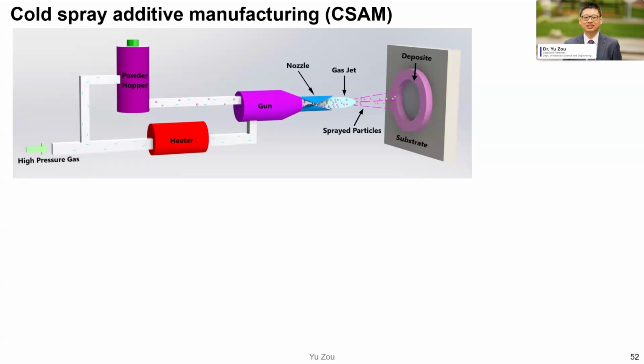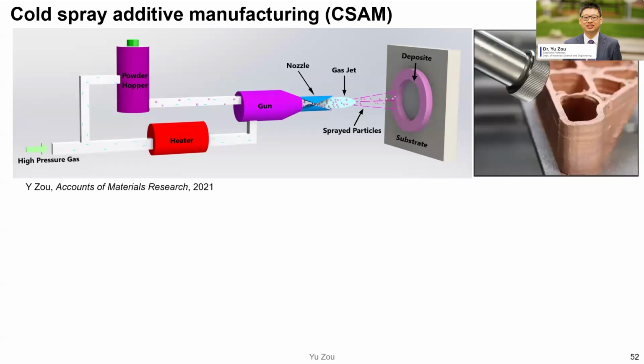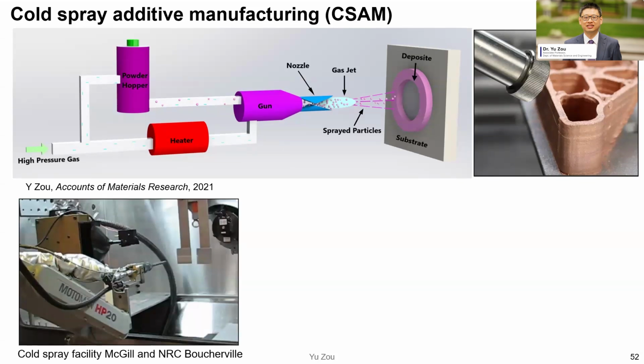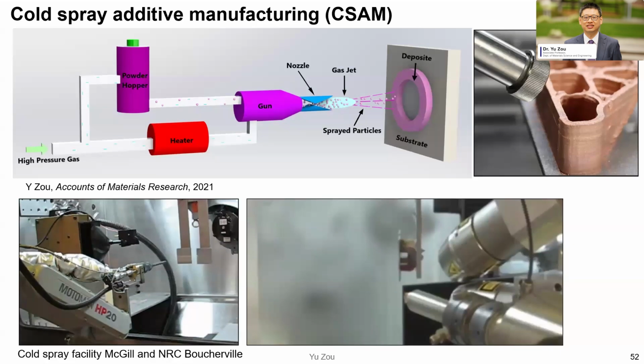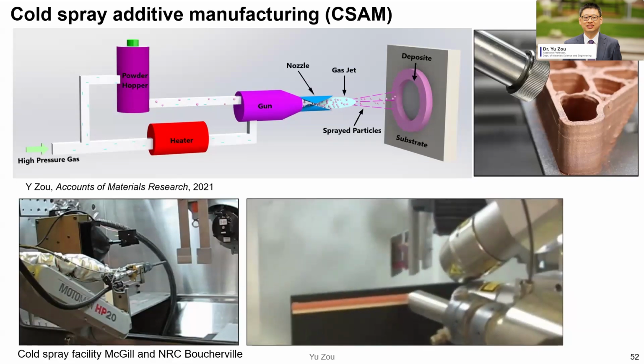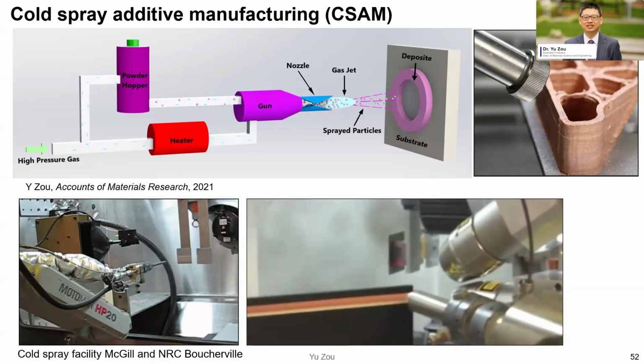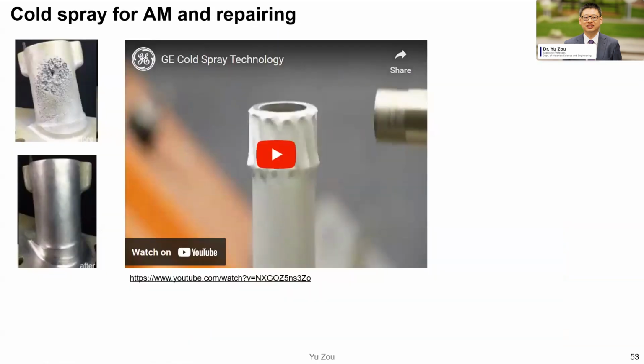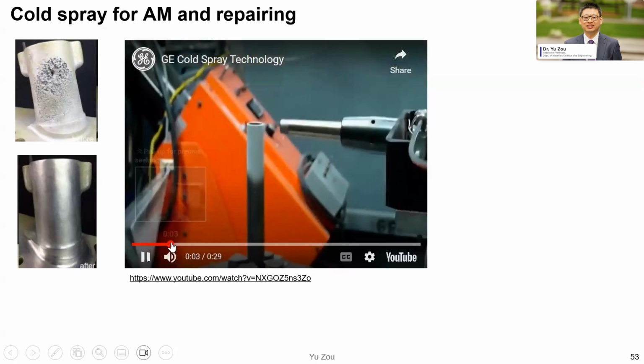Layer by layer, this is initially a coating technology, but we can also use it for additive manufacturing. This is a facility located in NRC Boucherville, and they can use this method to deposit the powder. So you can see this is copper powder deposited on a steel substrate. Okay, so cold spray can also be used for repairing. For example, this part has some surface pitting, and then you can use cold spray for repairing. And also, there's a video showing the cold spray technology.